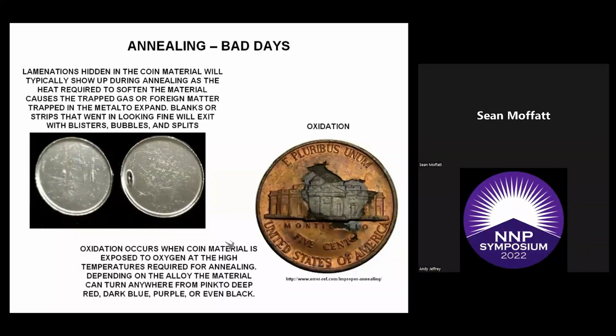Now, laminations, which are hidden, oftentimes will show up when you send the product through the annealing furnace as it heats it up, and the trapped gases or impurities that are below the surface heat up and expand. Then they start showing up as bubbles. Right? Also, if you don't have your gas mixture right going through there, you can have oxidation. And that's when the coin material is exposed to oxygen at the high temperatures required for your annealing. Now, depending on your alloy of the material, I've seen coin blanks come out of there, specifically sterling silver and 90% silver, come out there in all kinds of pretty colors, from pink, red, dark blue, purple, and even black.